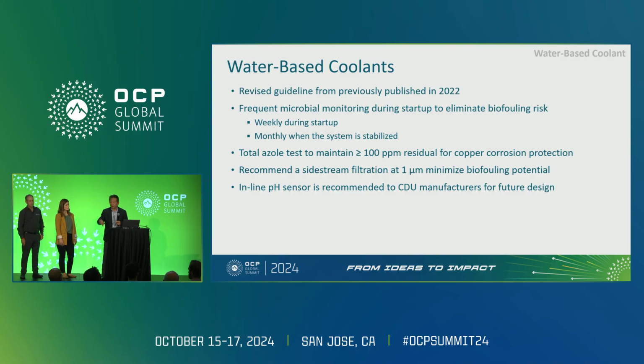For our discussion, we came up with a new suggestion for vendors. They should have an inline pH sensor, so you can monitor the pH shift as an indication that biofouling is starting to happen. So this is basically what we try to cover for treated water.